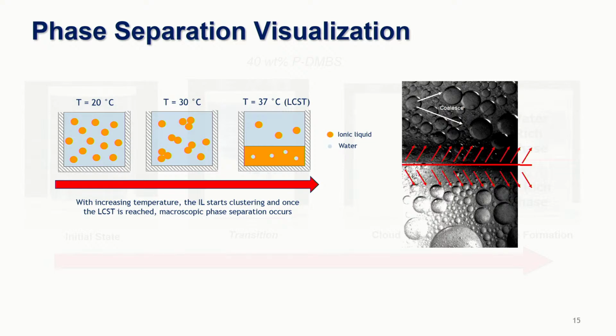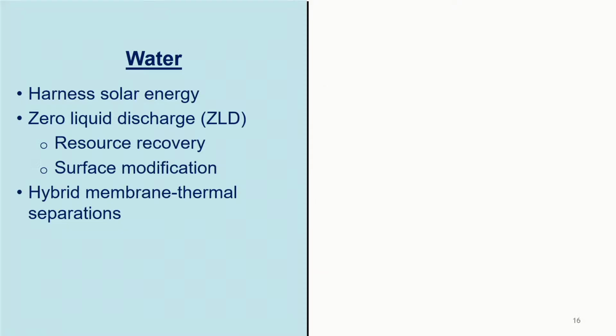So looking under a high-speed camera, we can see the phase boundary, and then we see these droplets of the ionic liquid phase, which are kind of trapped within the water-rich phase, and then we have the same down here. And so ultimately, these droplets or these ionic liquid clusters coalesce and form the second phase. And so we're trying to understand the kinetics of this process and how can we use different external forces in order to speed up that phase transition. So that's all the stuff we're doing on the water side.